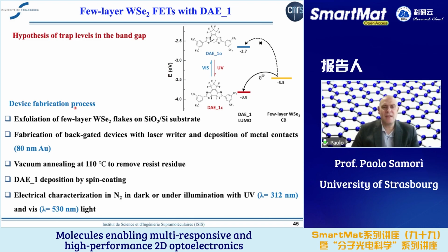We first of all exfoliated few-layer thick tungsten selenide and transferred it to silicon dioxide, fabricated back-gated devices with a laser writer, and deposited metal contacts on the top. Then we anneal this to remove all the residue of the resist that we used, spin-coat diarylethene, and then perform the electrical characterization in the glovebox under controlled light, which can be either in the dark or under UV or visible light illumination.